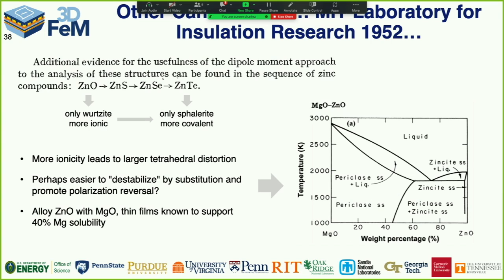So what could we throw in to zincite in order to poise the material on the brink of a structural transition? Well, I want to push it towards the rock salt structure to flatten that tetrahedra. Where on the periodic table do I have something like 6 coordination with oxygen? Magnesium. So we made a zinc magnesium oxide solid solution. The phase diagram is shown here.